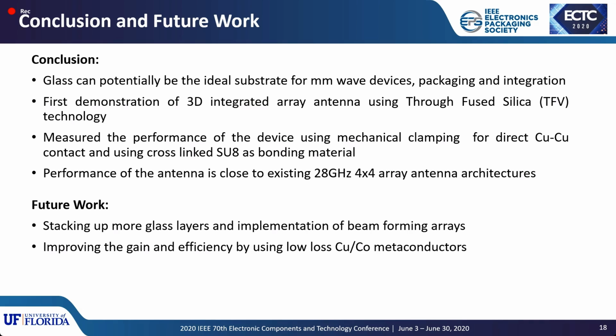In the future work, we are trying to stack up more glass layers and simultaneously reduce the thickness of each layer. And we are also trying to integrate beamforming array technology using materials like BST for changing the radiation pattern. And also the gain and the efficiency of these structures can be improved by using copper cobalt metaconductors instead of conventional copper, as copper cobalt metaconductors demonstrate less resistance at higher frequencies, especially at 28 gigahertz, compared to conventional copper. The gain and the efficiency can be significantly increased.